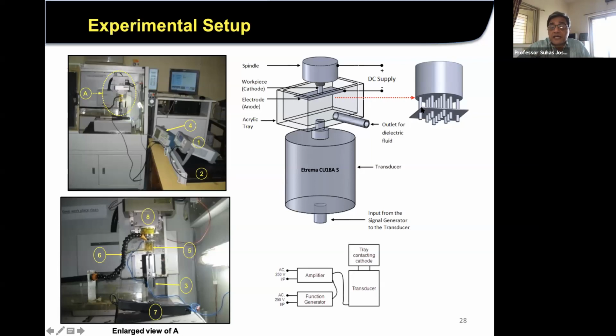The situation is something like this, with the whole thing being very, very small. What we did is we put an electromagnetic actuator at the bottom of the table, and we gave very low frequency vibrations to the table, and that has helped release the debris particles which get entrapped between the holes. And now we could make very long rods, without much wear on the electrode also. Sometimes the electrode holes get worn out and become larger. So that's also another problem.